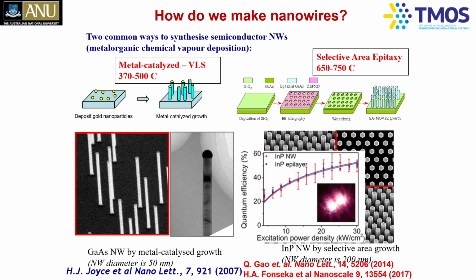For some applications, these ordered patterns are important, which I'll come back to and share with you. We have taken these indium phosphide nanowires, excited them with a laser pulse to generate electron-hole pairs, and looked at the light emission. You can see the higher the excitation power, the higher the quantum efficiency of these nanowires, and you can reach up to 50% or so. We compare these with the epitaxial layers grown under optimum conditions, the blue curve. They are very much comparable, indicating surface non-radiative recombination is not a major problem in the case of indium phosphide, which is not the case for gallium arsenide, where you have to do surface passivation to get any good quality light. Whereas indium phosphide is not a problem, which means they can be useful for making lasers and solar cells without having to do surface passivation.